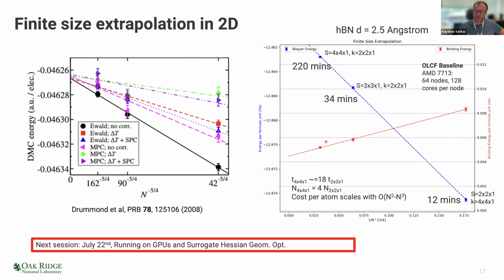So I think for the quasi-particle calculation, this may not be as favorable as this, because for a quasi-particle calculation or any excited state calculation, you would typically be looking at energy differences between two supertwists. That means you would calculate it for a single twist, and you need to go to much larger supercell sizes. So you need to run a longer QMC calculation for that particular twist where you're calculating the excitation.